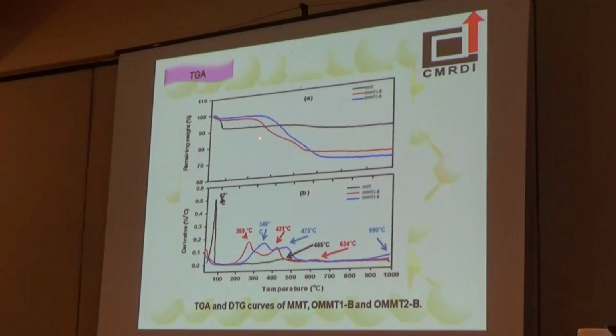While for the 2 modified clay samples, the decomposition takes place in 4 steps. For the 2 modified samples, the first step is due to the removal of water, the second step is due to the dehydration of the interlayer earth cations, the third step is due to the removal of the surfactant, and finally the fourth step is due to the removal of the hydroxyl groups.